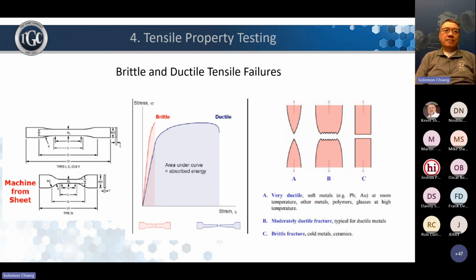And again, the test coupon shape is on the left-hand side. It is a dog bone shape to facilitate stress localization. And also, this helps with the alignment, because as I mentioned before, one thing about the universal tester is that a good one with a good fixture will help to align so that the force is applied at 90 degrees rather than twisted.